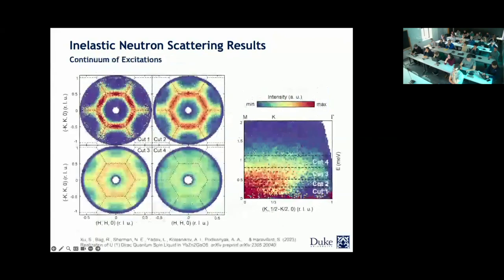Now, let's move on to the single crystal neutron scattering measurements. Here, again, you're looking at Q space, and this is energy versus Q. We saw that there is a continuum of excitations, similar to the 1114 compound. However, it has a little bit of a difference, which I will bring out in the next slides. Here you're looking at the cuts that we have made in energy. Cut 1 is the low energy. Here it's again picking up at endpoints, but it's not as significant as in the 1114 compound. Then when we go up in energy, it becomes more diffuse, and by cut 4 it's very diffuse.